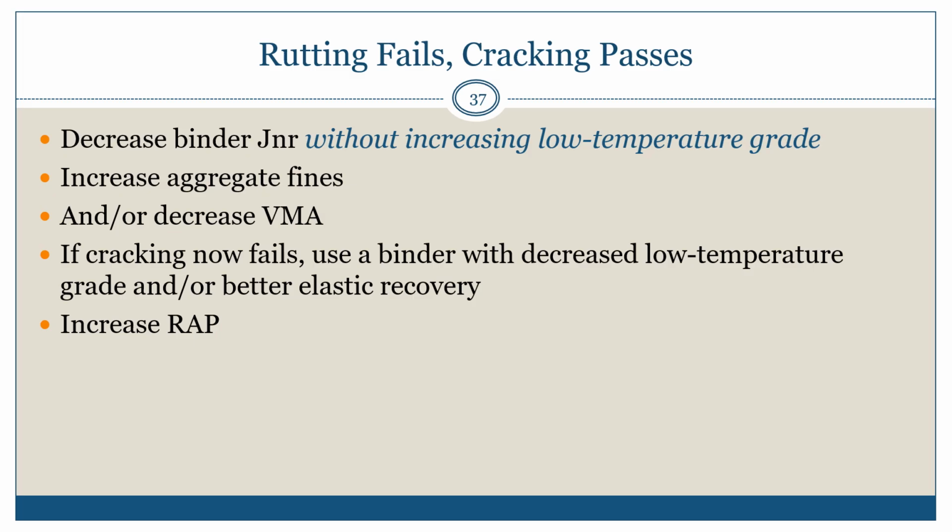We could also decrease the VMA. That will help with the rutting, but I wouldn't recommend this. It's not going to give you a huge increase in your rutting performance, and it will tend to decrease your fatigue and cracking performance.